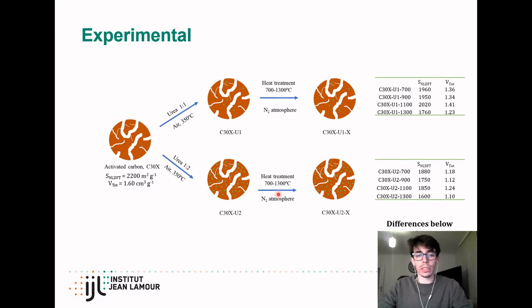The next slide shows a summary of the experimental section. As we can see here, the pristine activated carbon has been mixed with urea in a mass ratio of 1:1 and 1:2, leading to the functionalized carbon material, which has then been heat treated at different temperatures from 700 to 1300 degrees for obtaining several heat-treated carbon materials. The tables on the right show the textural properties of the resulting carbon materials, in which it can be observed that these properties, this texture, this porosity, is not modified by all this procedure in comparison with the textural properties of the pristine activated carbon, with differences below 5% or even 10%.